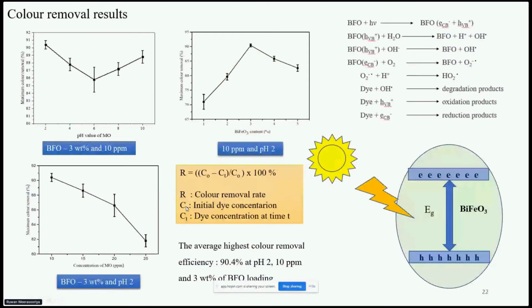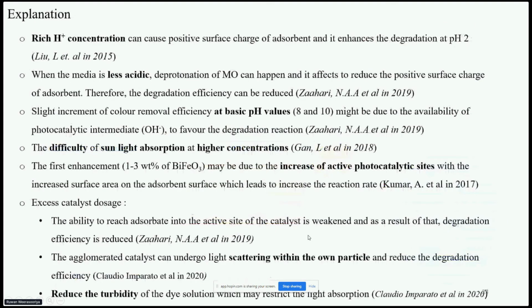These three figures show the maximum color removal efficiency variation with pH value, bismuth ferrite content, and concentration of methyl orange. According to that, the average highest color removal efficiency was obtained as 90.4%. That was obtained at pH 2, 10 ppm, and 3% of bismuth ferrite loading. So according to the observation, at pH 2, the degradation is highest.